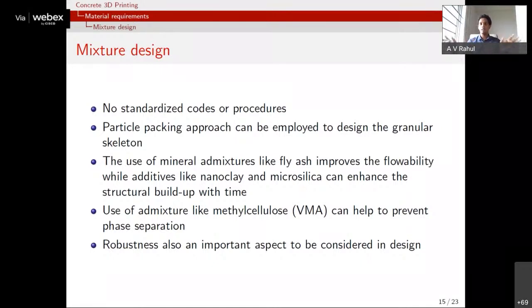And that workability change may be just sufficient to cause the mixture not to print properly. So that robustness range you have with these kinds of mixes is very narrow. So how do you address this issue is also something that we need to look at. In fact, studies have indicated that certain chemical admixtures like methyl cellulose can be introduced, which can provide a wider range, so the mixture is able to remain printable over a wider range and show more robustness when you incorporate these types of admixtures. So this is also an important aspect that we need to consider when you perform the mix design.